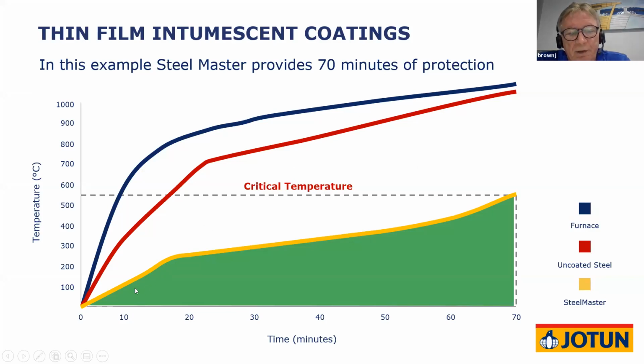That's unprotected steel, the red line, and this is temperature. If we apply an intumescent coating, as you can see, this yellow line starts to swell here, and then after 70 minutes, it's given 70 minutes fire protection. So that's the swelling action. It's stopping the temperature rising.